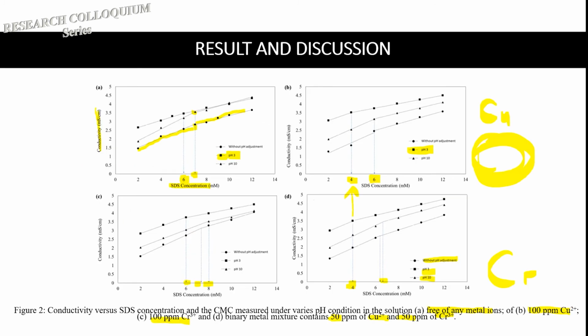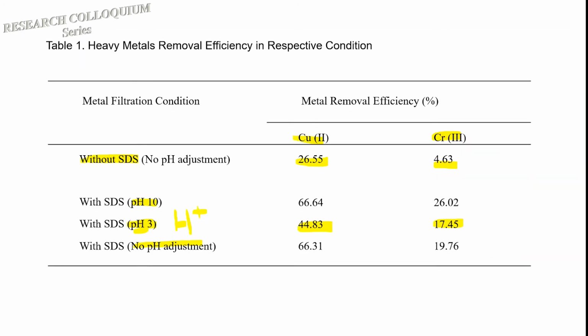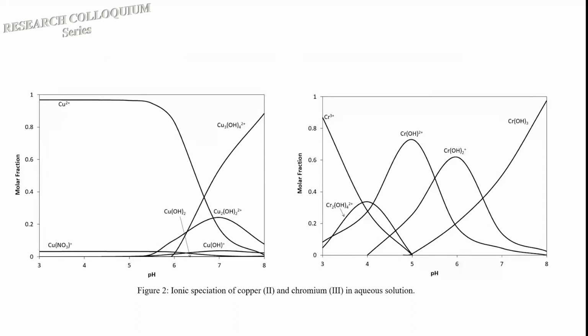The first explanation, actually I can explain it based on the conductivity over here, based on the CMC over here. We observe that in the binary mixture, it seems like the copper actually is taking the initiative to bound with the SDS micelle. On the other hand, I also can explain it based on the ionic speciations of both copper and also chromium. You may realize that within the range of the pH from pH 3 until pH 8, the copper actually is quite consistent, actually is steadily presented as Cu2+ from pH 3 up to pH 5. However, beyond pH 5, the copper hydroxide complexes will be formed.